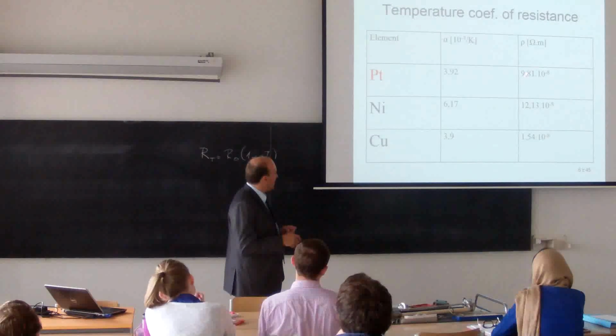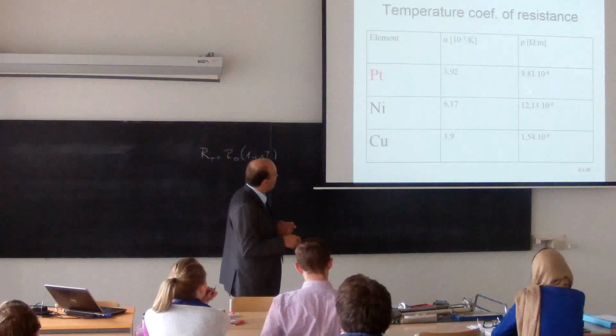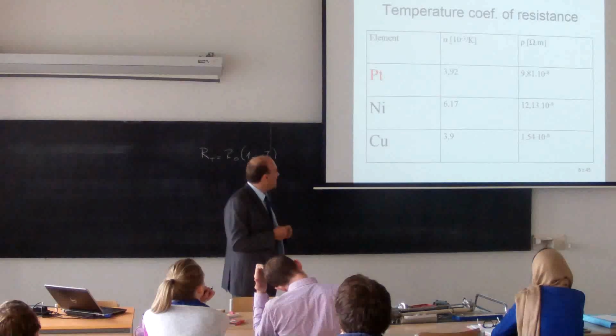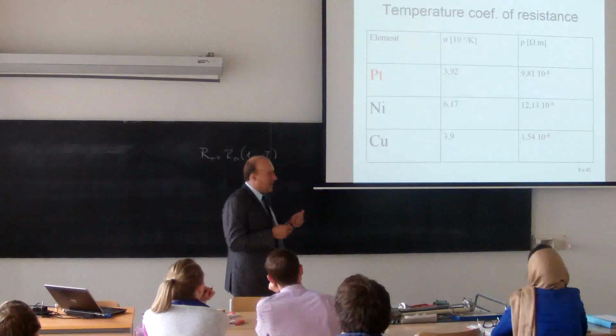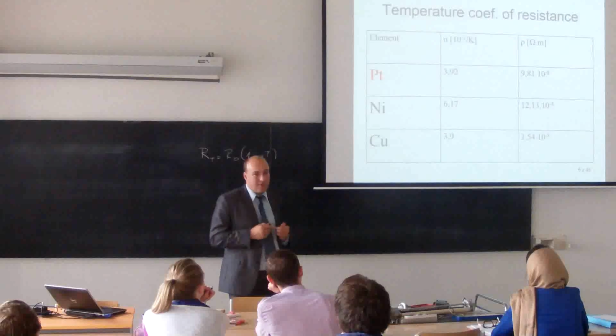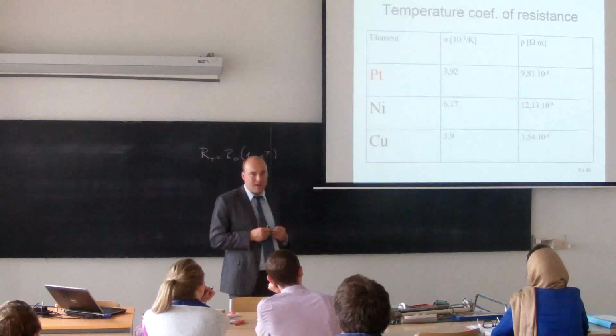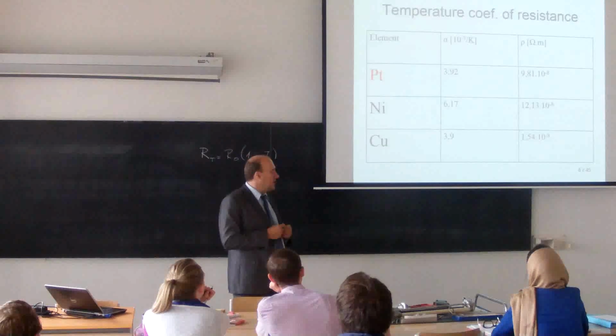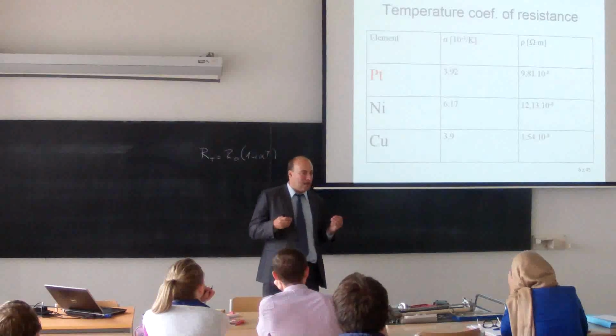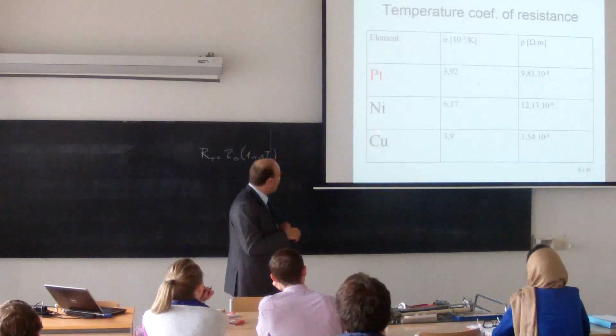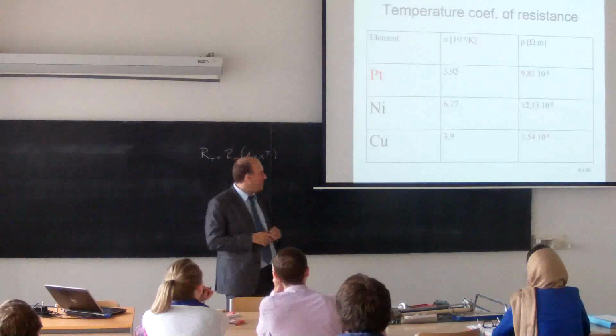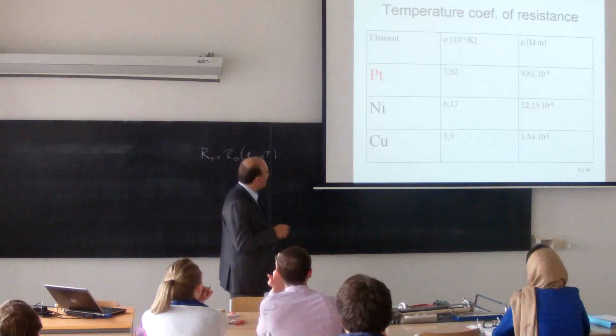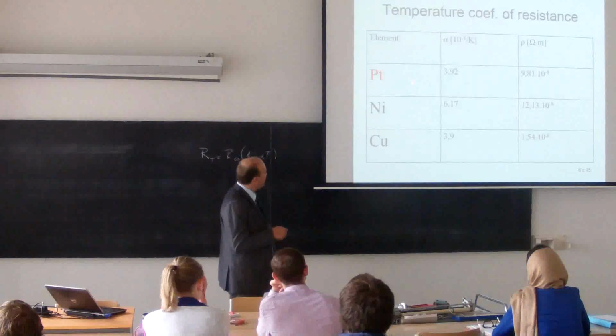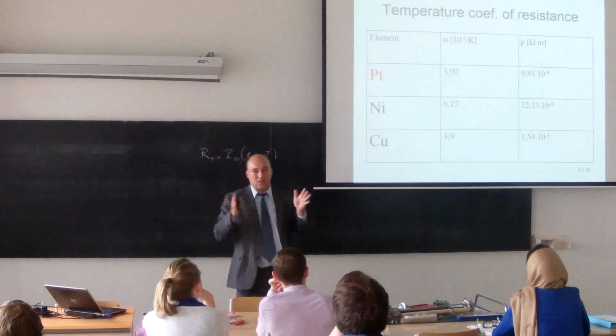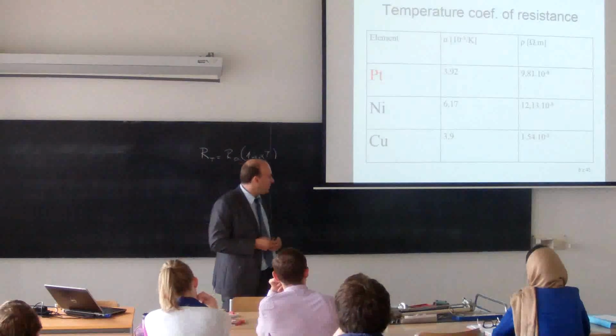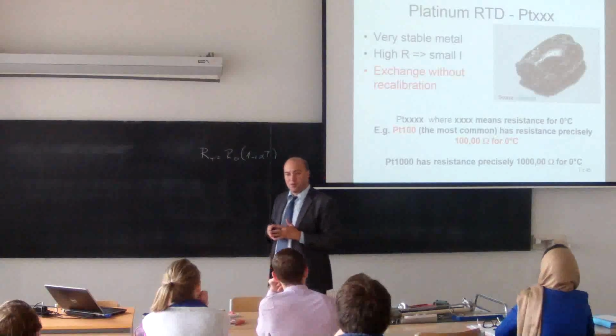And then, if we compare the last part, the resistivity, we will see that platinum and nickel have approximately the same value. It means that a wire of the same length and of course the same diameter, from nickel and platinum, will have approximately the same electrical resistance. But copper with the same length and diameter will have much lower electrical resistance, which will mean that if I were to build a sensor with, for example, 100 ohms, then I would need a copper wire 10 times longer, which would be a problem to fit inside the housing. So copper is not very good for this reason. Platinum and nickel have relatively high electrical resistance, which will give me a smaller sensor that will fit inside the housing.